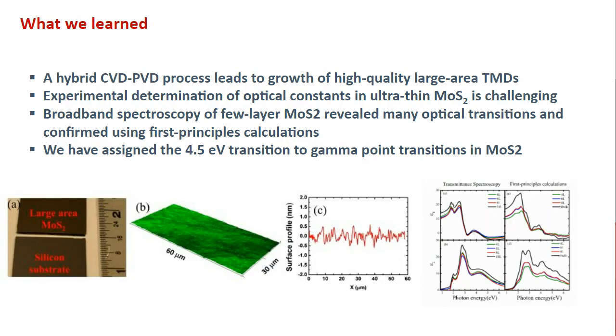So to summarize our MoS2 project, what we have shown here is that we developed a hybrid process to grow these materials in large area form, where we are taking the good part of sputtering, and also we are doing a second step using a process called sulfurization, which is sometimes called the chemical vapor deposition process. So it's a hybrid CVD PVD, and then we analyzed the broadband optical properties of MoS2 and found many interesting transitions. One of them, which we think is not reported in the literature as far as few layer MoS2 goes, and we have assigned this transition also.